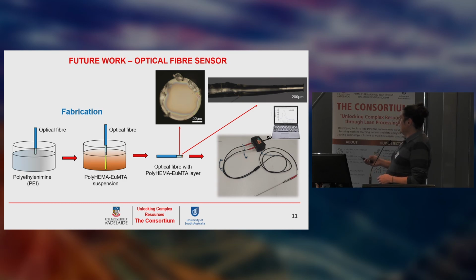So this is where Piotr is up to. He's polymerizing the composite onto the end of this fiber optic. And this just involves dipping the fiber optic into a solution of the monomer and the MOF, and then firing a laser light down the actual fiber optic to polymerize the composite onto the end of the fiber optic. He hasn't yet got to testing that. He's still optimizing this process to get a nice, thin, and consistent film on the end of the fiber optic.